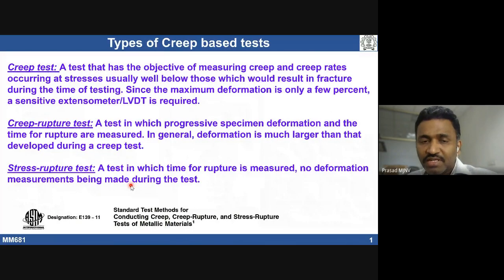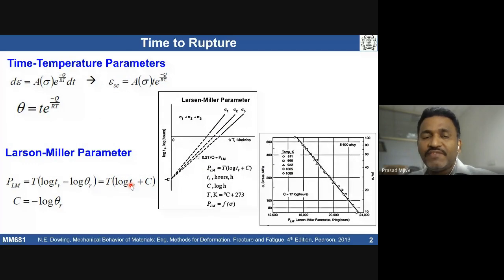See slide 1 now. Okay, we had a discussion on the creep deformation behavior of materials. Then we had a discussion about the creep rupture behavior of material. The Larson Miller parameter is an important parameter which describes the time-dependent temperature compensation. By taking time and temperature, one will get a Larson Miller parameter. For a given Larson Miller parameter, what is the stress we can apply to the material so that the component can be safe? So for design purposes, people use the Larson Miller parameter to understand the effect of time and temperature on creep rupture or creep deformation of a material.